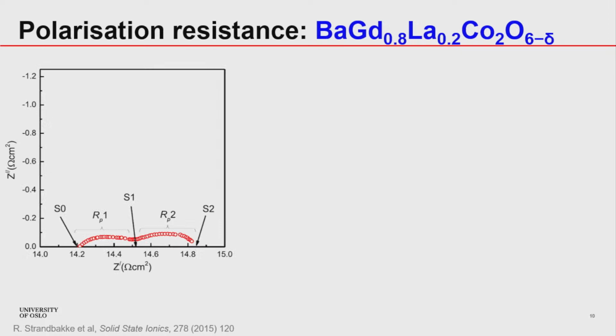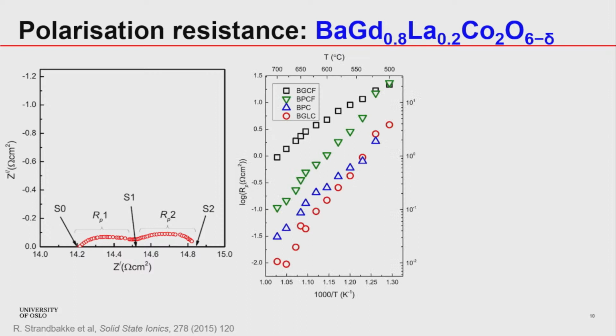Next is to see the polarization resistance of the BGLCs. I'm assuming that everybody is well versed with Nyquist plots. This Nyquist plot just says that we have two electrochemical processes related to the polarization resistance. If we plot the RP versus temperature, what we see is that the BGLC, which showed the highest hydration, is also showing the lowest polarization resistance. But one important thing is that the praseodymium, which did not show any hydration or very low hydration, is still showing almost similar RP values at low temperatures. So this indicates that maybe we need to understand more about how many protons are needed to have better performance in these kinds of systems.